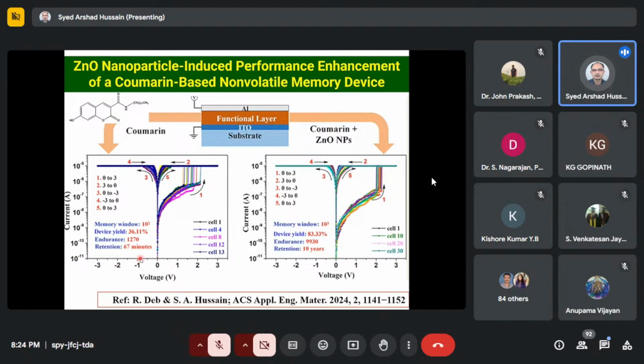Okay, and retention, the stored information, we have seen that it can be stored even for more than 10 years. Actually, we measured physically around 200 days, and then we did some extrapolation and fitting studies, and we showed that it can retain the data without much degradation of the resistance state, even up to 10 years, which is very good for real practical applications.